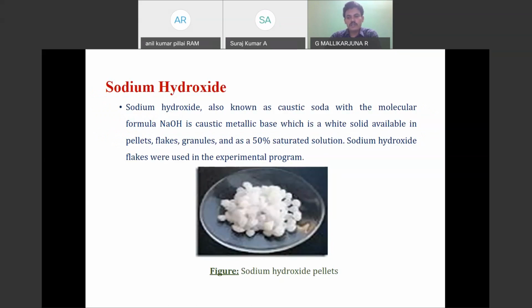These pellets we add for an 8 molar solution. We take 320 grams, and we prepare a 1 liter solution. And the sodium silicate to sodium hydroxide ratio we vary from 1.5 to 3. Many researchers have concluded that the maximum strength is obtained at a sodium silicate to sodium hydroxide ratio of 2.5.